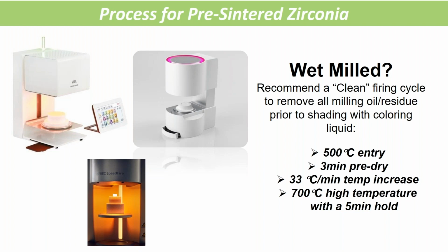So if it's wet milled, you can't introduce it into a sintering furnace when it's wet. You will end up with an explosion, if you will, fireworks of your zirconia, because that inside liquid has nowhere to go. It'll give you a heat tear, just like we do with ceramics. It'll create a heat tear, but because the zirconia is so dense, it has nowhere really to escape fast out. So it will kind of blow out. So if it's wet milled, you want to do a clean firing to get rid of all the oil residue, as well as dry it out.